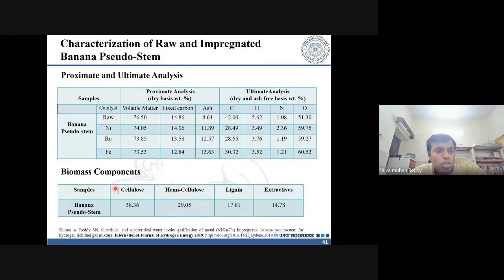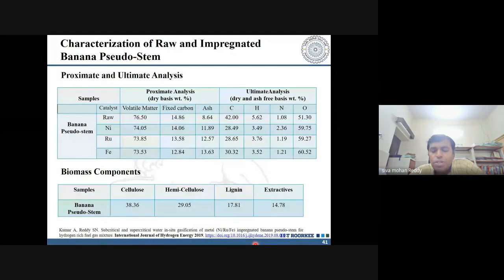Not only that, we have already quantified the biomass in terms of its essential components, that is cellulose, hemicellulose and lignin, and also the extractives. The banana pseudostem has a cellulose content of 38.36, a hemicellulose content of approximately 29, a lignin content of 17, and extractives of around 15%. So these three parts contribute to a greater extent, where you are going to convert them into your gaseous fuels.